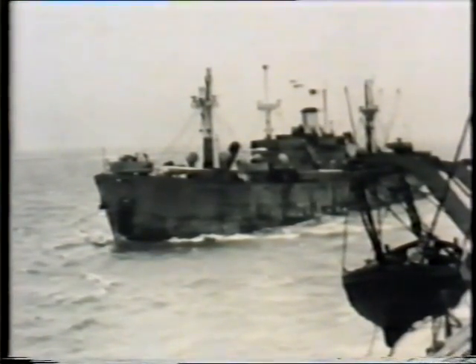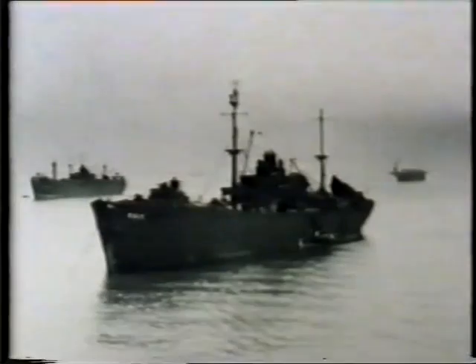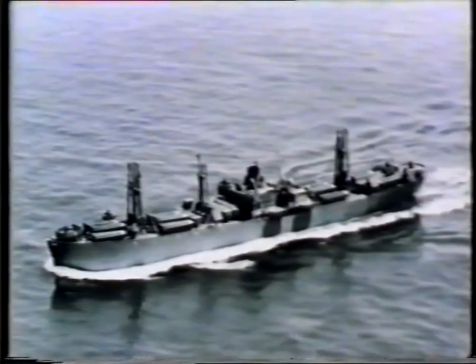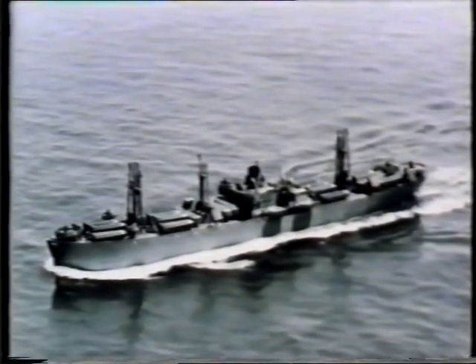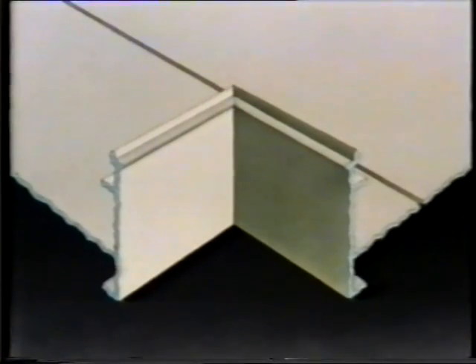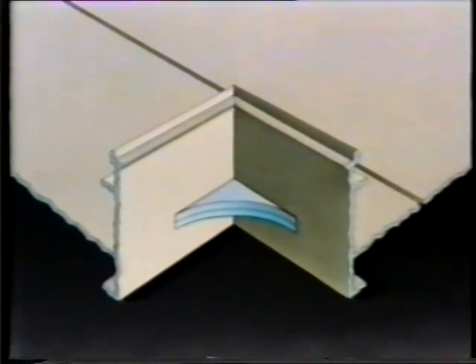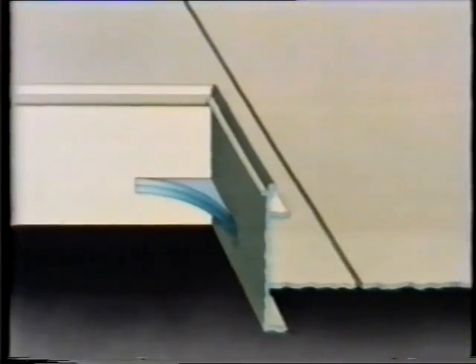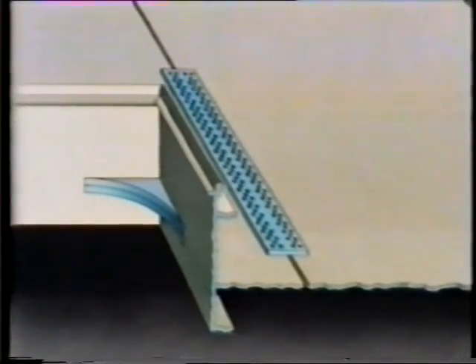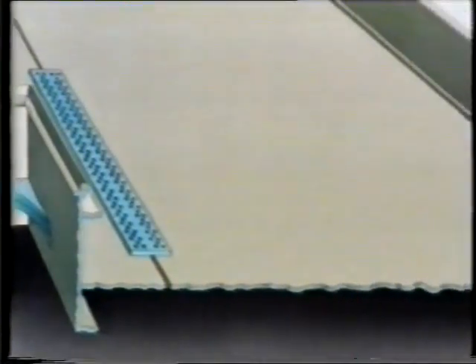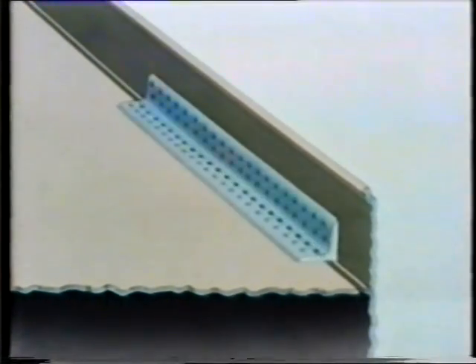So what was to be done? There was no easy way to improve the quality of the welding quickly, and higher grade steels just weren't available. But something that could be improved was the design. In ships that were already operating, the hatch corners were given a somewhat makeshift reinforcement to reduce the stress concentration. Subsequently, the design of all ships was to include rounded corners wherever appropriate. Also, crack arresters were built into many ships. Strips of high-toughness steel riveted to the hull over which a crack couldn't jump. These were introduced in a number of locations and proved very effective.